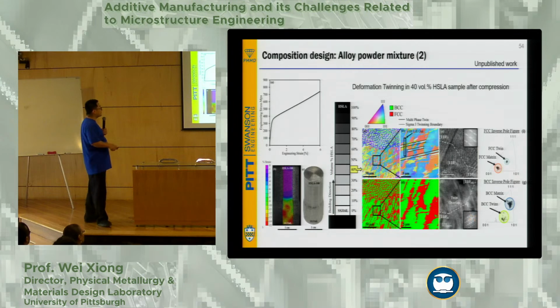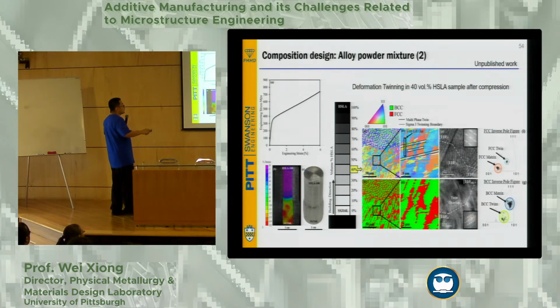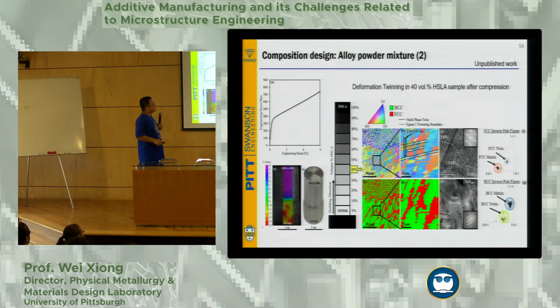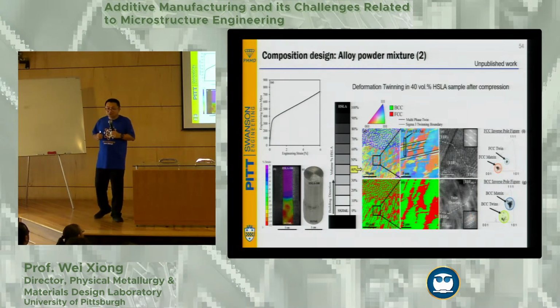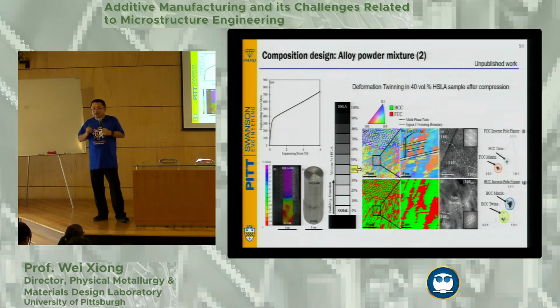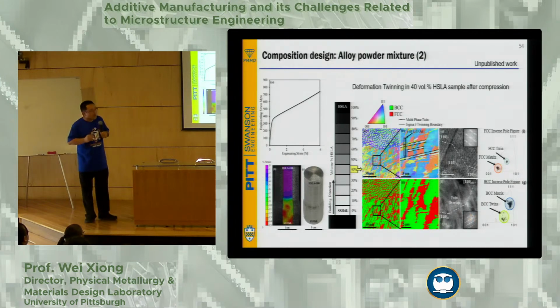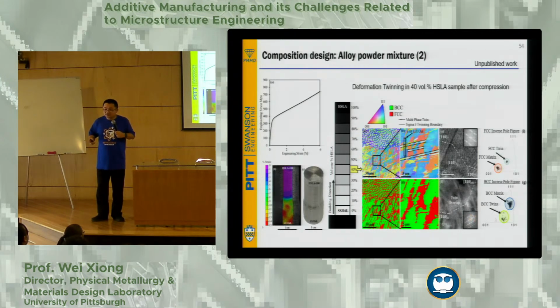And why it happens is because during the melting process of the laser melting, you can introduce some segregation. With the segregation, some parts are easier to form martensite, so they form martensite. Some parts did not have enough formation of martensite, they stay as austenite. And then the retained austenite has a little bit well-controlled austenite stability, so after you press it, you start to form twinning and TRIP effects, forming new fresh martensite.